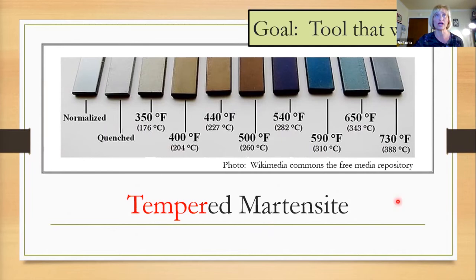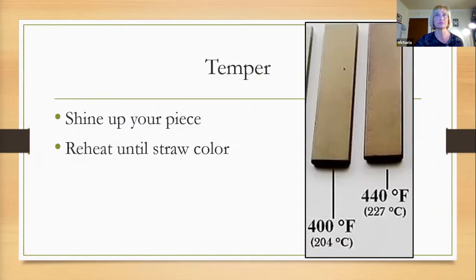So the color we're looking for is this straw color. Straw color right here, darker straw at 440. So the steps to temper: shine a piece, reheat until you see that straw color. And you can do that in an oven. The temperature we're looking for is 430 degrees. And in an oven, you can get to 430 degrees, put your piece in for 15 minutes for every 1/4 of an inch wide. Or we put the two steps together with one heat, and we heat our piece up past the transformation temperature. We quench it, and then we shine it up, watch the colors run.